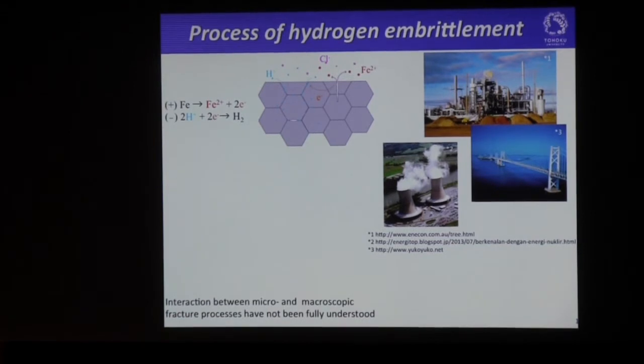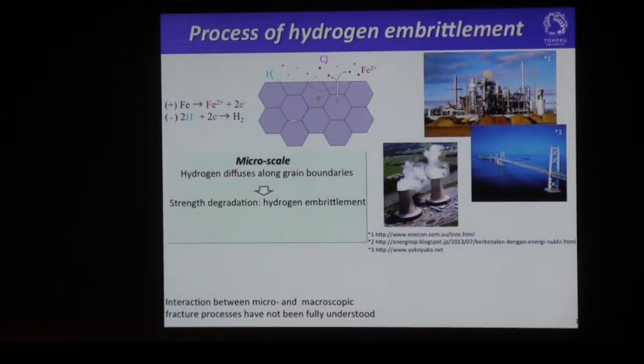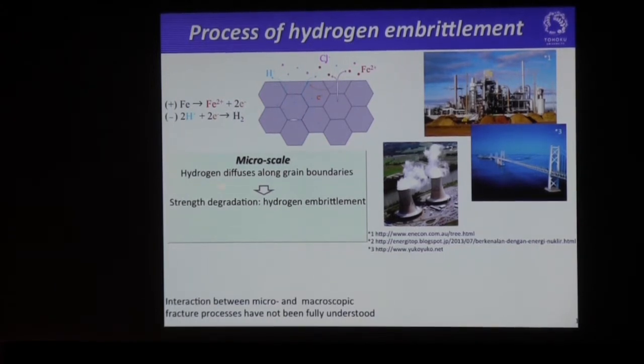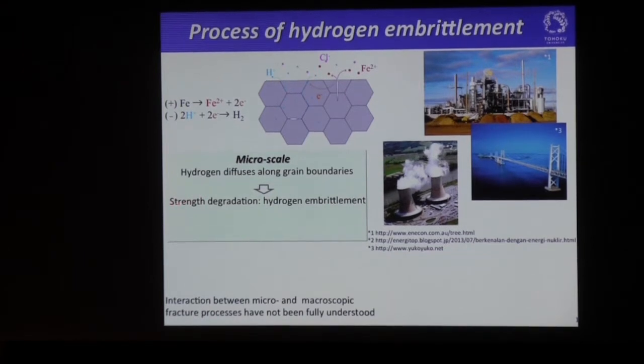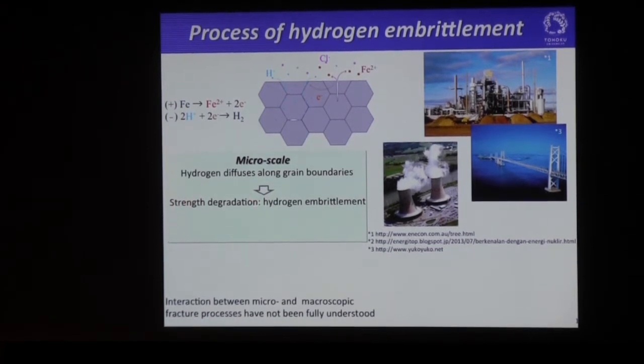As you know, hydrogen is a very important element in energy engineering. When hydrogen diffuses along the grain boundary in a polycrystalline aggregate, the material suffers from strength degradation, which may be caused by this kind of electrochemical reaction. This strength degradation is called hydrogen embrittlement, okay?